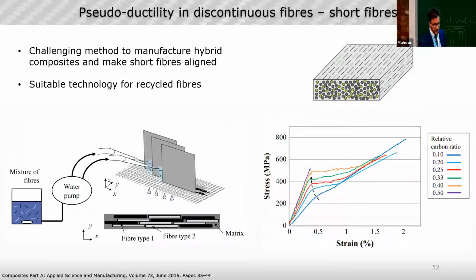Short fibers, and now we are in the hybrid composites category. Short fibers are one of the easiest ways to achieve pseudo-ductility, because in this case the fracture process is based on the gradual fracture of the short fibers. So the pull out and fracture of the short fibers generate the different grades of pseudo-ductility. This trend depends on the grade of the hybridization. In fact, I want to highlight how the initial stiffness of the material increases as soon as we increase the content of the carbon. So more carbon, of course, since the carbon is stiffer than the glass, increases the initial stiffness.